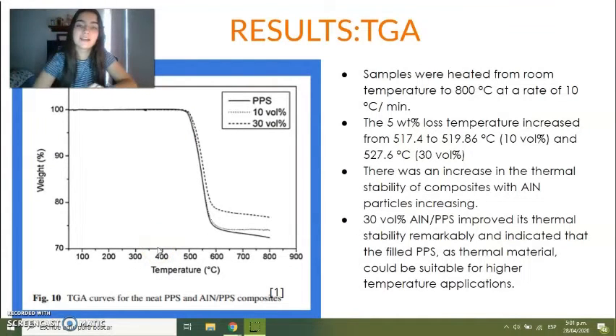I'm going to explain the TGA diagrams for PPS and AlN/PPS composites that are shown in figure 10. First of all, the 5% loss temperature increases from 517 to 519 degrees, as we can see on the graphic. So we can conclude that there was an increase in the thermal stability of the composites with increasing AlN particles. An explanation for that could be the high heat capacity and thermal conductivity of AlN, which would mean that the composite absorbs heat in a better way, resulting in PPS chains undergoing degradation at higher temperature.